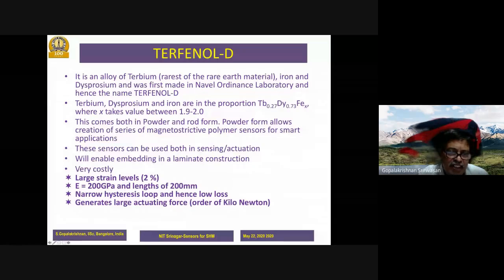The advantage is this comes both in powder form as well as in a thick rod form. The powder form is very useful because you can powder it and mix it with an epoxy matrix. You can actually make a sensor and embed it into a composite. These sensors can be used for sensing as well as for actuation, and as I said, this enables laminate construction. But it is very costly. How costly is it? One gram of Terfenol is equal to 8 times the cost of gold. But that cost can be somewhat justified because it has large strain. That means it can give a large block force. The block force I can generate through actuation is kilonewtons of force.